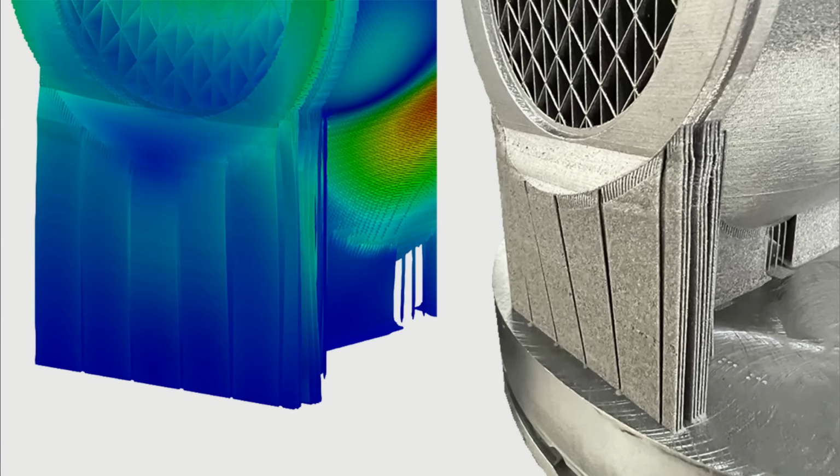So what's going on here? Is there a shift line in there? It looks like it's bent. Yeah, so essentially the bottom of the part is separate from the rest of the part behind it, and as it started building, the heat is actually moving the part around in the powder bed. That sharp line that you see is where it connects to the rest of the part, and then it gets rigid from there because it's solidly connected to the build plate. But the problem was that these thin, tall supports were able to just walk around as we were building it.